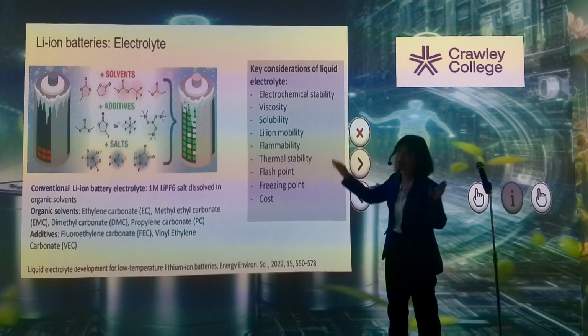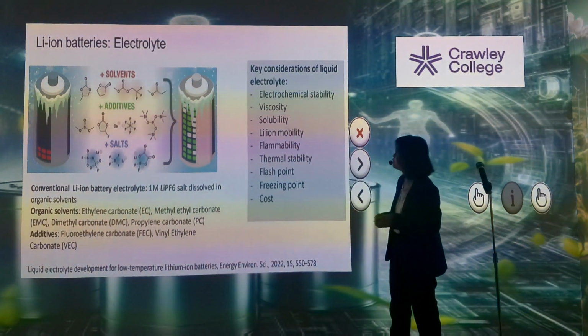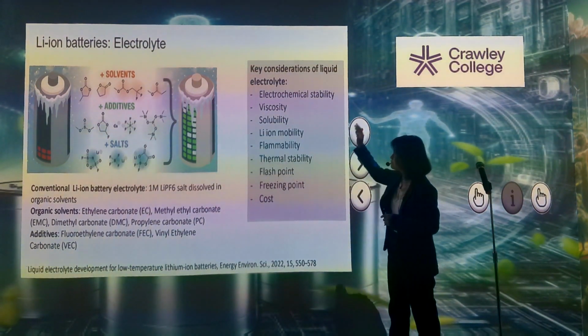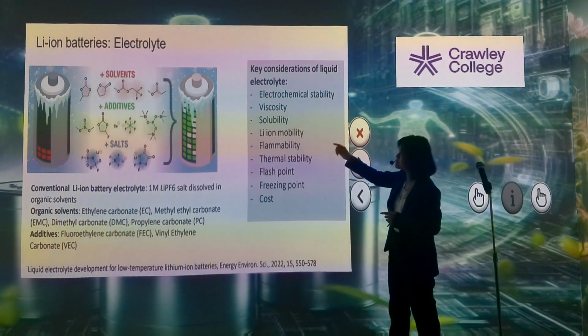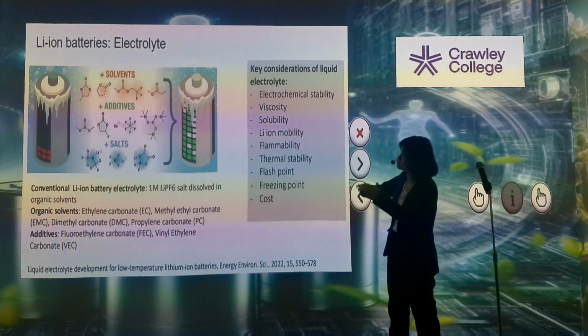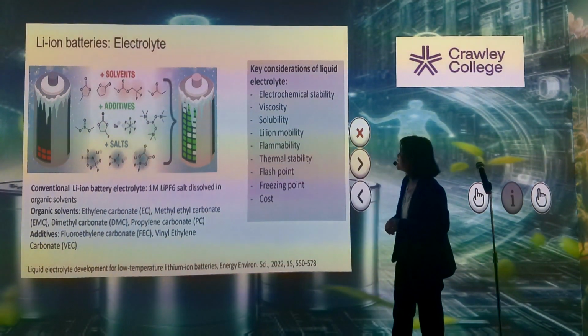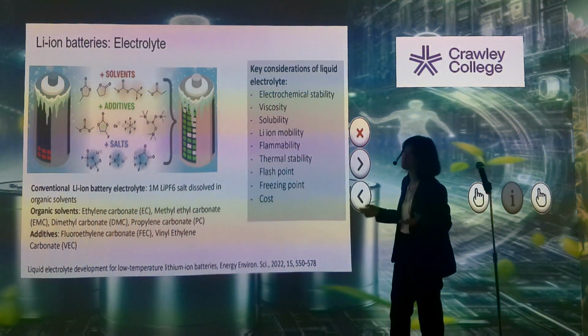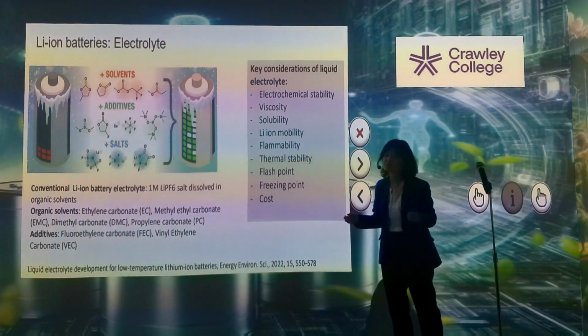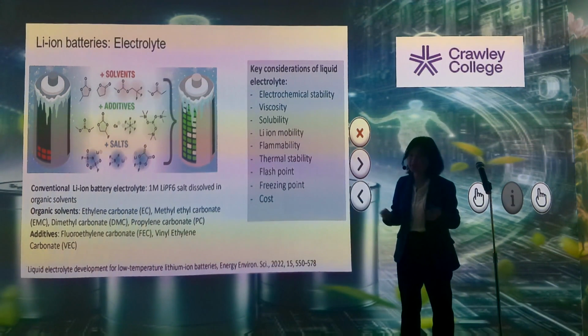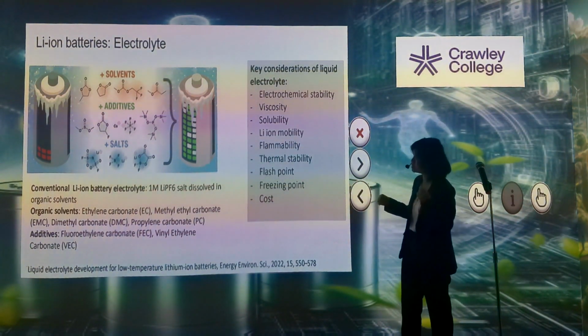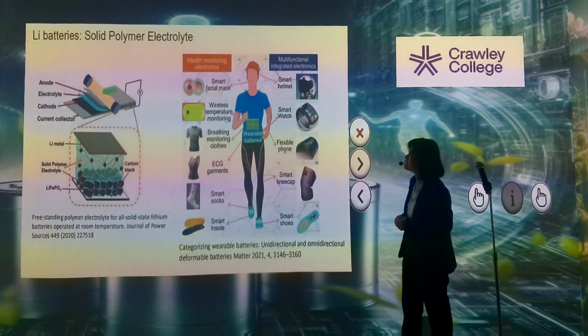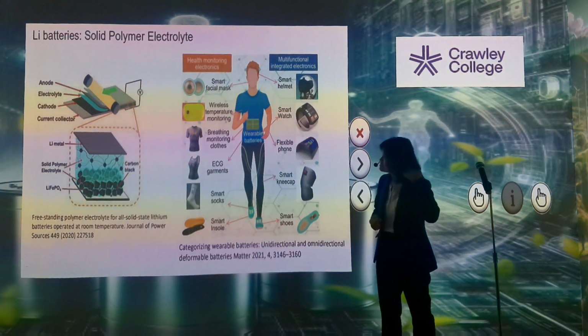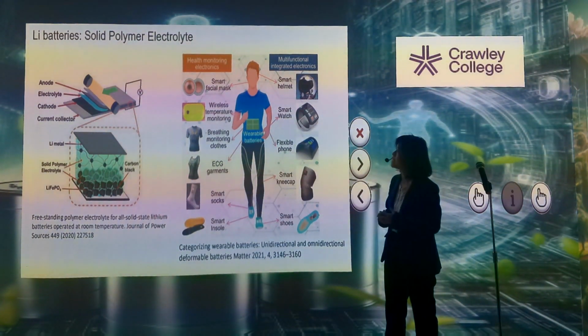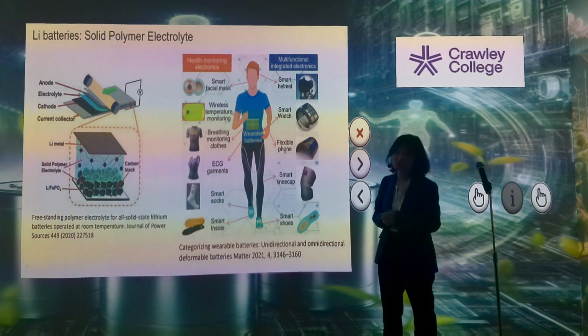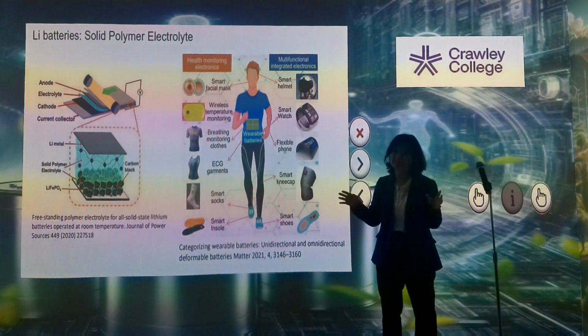There are a lot of properties that we want from the liquid electrolyte. They must be stable under that voltage condition, typically 4 volts for the cell, and they need to have a good mobility of lithium ion within that liquid electrolyte so that it can move between the two electrodes, and they need to have some kind of thermal stability. However, currently the organic solvents are very easy to combust. That's the safety issue with liquid electrolyte lithium-ion batteries. And so to have safer batteries, people have now come up with the idea to develop solid polymer electrolyte to replace that organic liquid electrolyte.